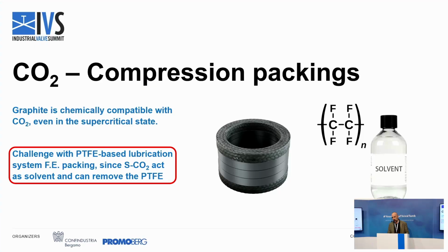On a side note, we are finishing the test with a new kind of lubricant in the compression packing rings, which have less than 0.1% of PTFE in the lubricant. So if we consider the whole packing, it's basically zero PTFE in the whole volume. That means that this friction and this loss of sealing capabilities is not present as in the compression packing with PTFE as lubricant. Okay.